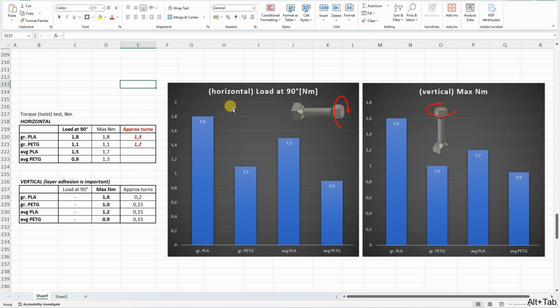Horizontally printed, the graphene-reinforced filaments are stronger compared to the base average materials. Vertically printed, the PLA is by far the strongest, and probably we have a similar ratio here. The graphene-reinforced PETG would be even better if it had a better layer adhesion.